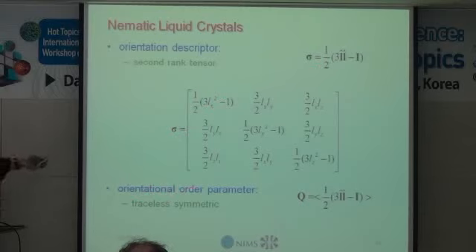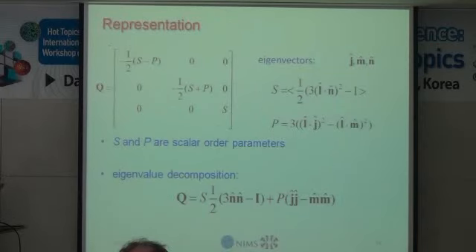So each particle in a system has an associated sigma orientation descriptor, and the average value of that is the order parameter tensor. And this then sort of carries the first relevant level of information about the orientation of the system. Now this is a symmetric traceless tensor. It can be diagonalized, and one can then write the eigenvalues in this way because it's traceless. So S is a scalar eigenvalue that basically tells us to what extent the individual symmetry axes are parallel with the average direction, and S can go from 1 when everybody is aligned. But when all the molecules are perpendicular to this unique direction, then S is -1/2. So S goes from -1/2 to 1.